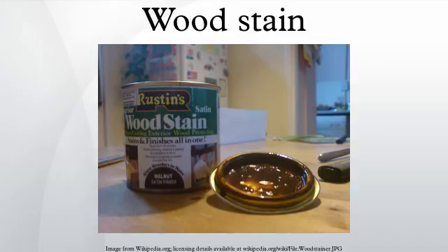Different wood species stain differently. The overall color and shade is a result of a combination of the stain and properties of the wood. For example, although medium to dark stains tend to look blotchy on maple, they get deeper and more glowing on cherry, with a more consistent coloration. Stains that are fast drying will be difficult to apply in hot weather or in direct sunlight. Stains that are slow drying will be difficult to work with in damp and cold conditions due to a greatly lengthened evaporation and curing period.